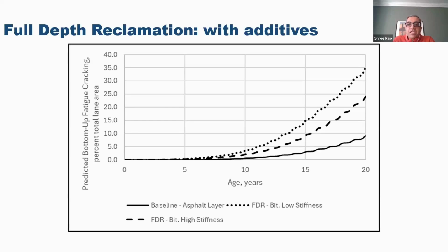And then the bottom-up fatigue cracking, again, because the properties are different for the different layers. The baseline has a lower bottom-up fatigue cracking, but the full depth reclamation layer, when it has low stiffness, has the higher level of bottom-up fatigue cracking, and when you increase the stiffness, then it has a lower level of bottom-up fatigue cracking.